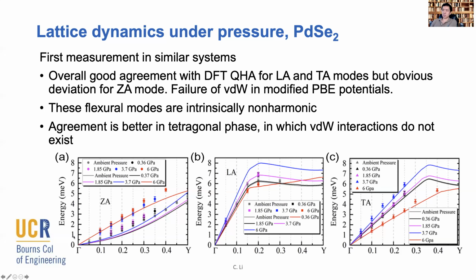So as you can see, initially we have a relatively flexural mode, which shows a nonlinear behavior in dispersion. It's actually not exactly quadratic. It's actually something in between. And once we apply the pressure, you can see this branch stiffens slightly initially. But once we reach the pressure around 3.7 GPa, the phonon stiffens a lot. And something happened between those two pressures. But this is still in the low symmetry phase.